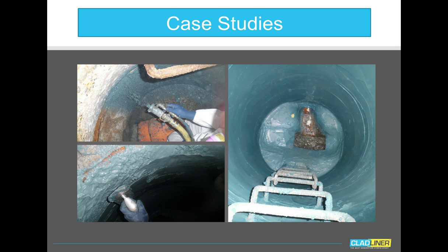The city of Bremerton, Washington had a manhole that was about 10 foot deep that needed to be repaired and restored for hydrogen sulfide and inflow and infiltration, I&I. In this case, because this was precast concrete and the manhole itself was in relatively decent shape, once all the leaks were stopped, the Cladliner was applied at a 1/4 inch, and as you can see, it was spray applied and then back troweled.